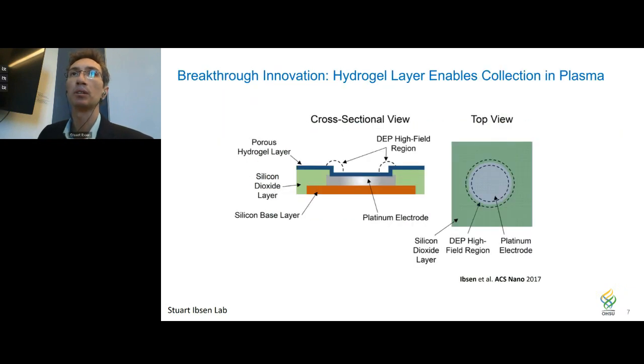Now, the breakthrough innovation that Biological Dynamics introduced to these chips was the addition of a porous hydrogel layer over the surface of the electrode. Here we're looking at the electrode in cross-section. The electrodes are platinum, and when metal comes into direct contact with a very salty liquid like plasma or blood, typically you'll get instant electrolysis. So you'll get all these electrochemistry things happening. You'll get the production of free radicals that can destroy your sample. And you also get the production of bubbles of oxygen and hydrogen that will ruin your sample if you get too many bubbles.